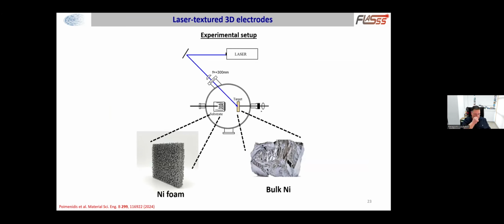Our research also extends to 3-dimensional structures, in an effort to study materials that would further increase the hydrogen production performance. In this case, we employed pulsed laser deposition, which is another standard method based on lasers to process materials. We used as a substrate a nickel foam, which is commercially available. Basically, it is a sponge-like, heavily porous material, and we shined the laser beam onto a nickel target in order to ablate it and create a lot of nanoparticles that were afterwards deposited on the surfaces of this nickel foam network.